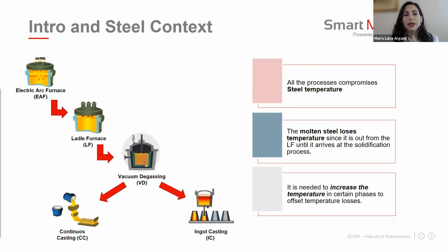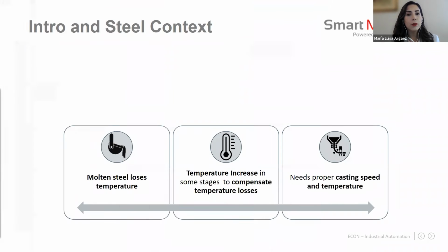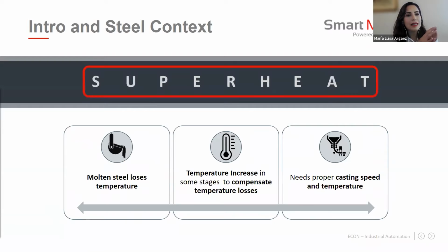And it is crucial for the steel to arrive at the tundish with proper temperature, to have a proper casting temperature at an acceptable CCM speed. Well, but how do we compensate for temperature losses since the steel is out from the ladle furnace? Well, we compensate for temperature losses by giving a superheat to the molten steel in the ladle furnace to guarantee an optimum steel temperature to the final casting process.